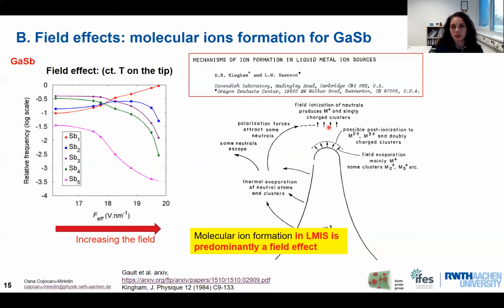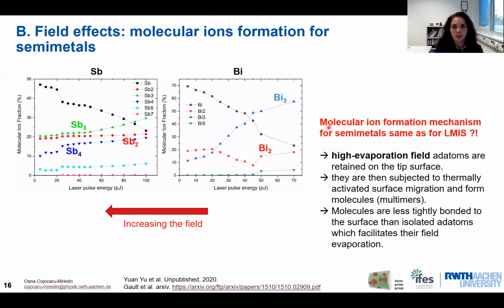But what is important to note here is that the molecular ion formation in the liquid metal ion sources is predominantly a field effect. If we take some other example of semimetals like antimony and bismuth, we have seen the same behavior in our lab. We have seen the presence of molecular ions and how the fraction of molecular ions changes very much when we increase the field. So we see typically that the fraction of these molecular ions decreases when the field increases or when the laser energy is decreased. So is the molecular ion formation mechanism the same as we have seen for the liquid metal ion source model?